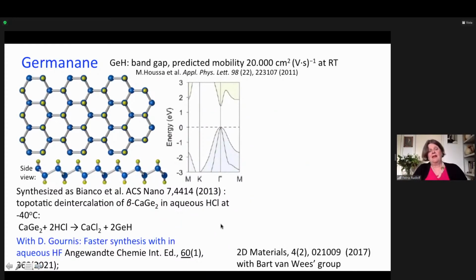You can also play these games with other 2D solids. A material that we have worked with quite a bit is germanane. So what does germanane look like? If you look from above, it is also a hexagonal structure, but every germanium atom is terminated by hydrogen. It was first synthesized in 2013. One starts out with a germanium calcium compound, and then with acid, one gets the germanane.